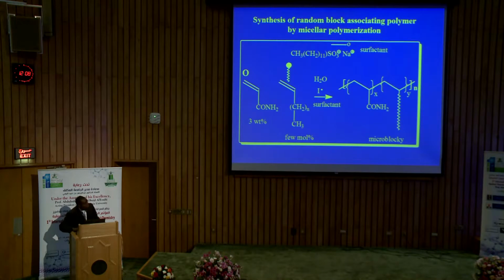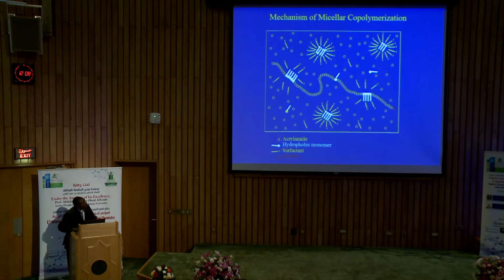Now, generally, associating polymers are formed by micellar polymerization, and a typical example is the solution polymerization of acrylamide, which requires just 3% of the monomer with a few percent of the hydrophobe to form microblock polymers. This is a typical representation of micellar polymerization. The polymerization is initiated in aqueous medium, and the hydrophobes are trapped in a micelle. As the polymerization continues, it eats the micelles, and the hydrophobes are generated in the form of blocks, which are represented as white hydrophobes. But this type of polymerization is not available for our system.